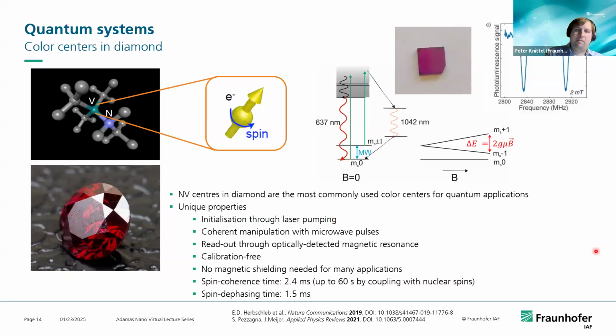But in addition to that, there are a few things that are of high importance. One thing is that this magnetic field splitting is completely independent from your diamond in principle. So you can do this measurement calibration free. It only depends on natural constants. You don't need a magnetic shielding because you can compensate for the Earth magnetic field.